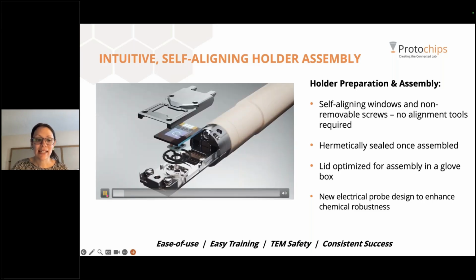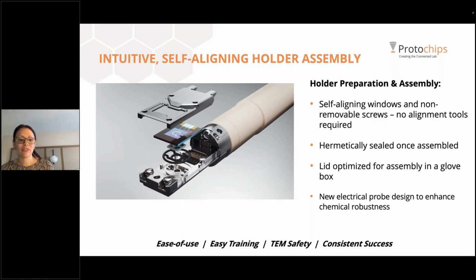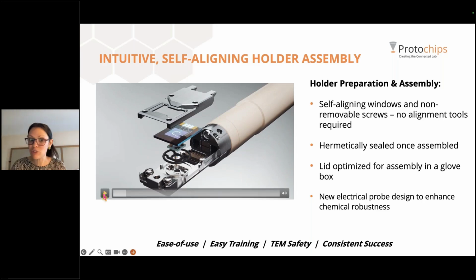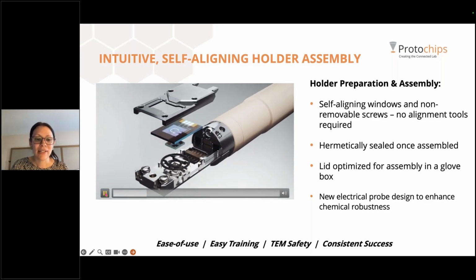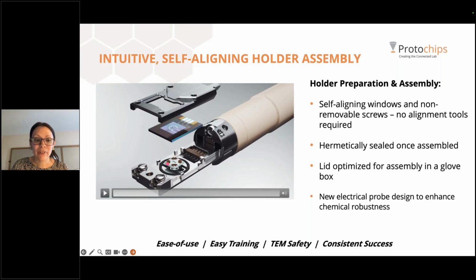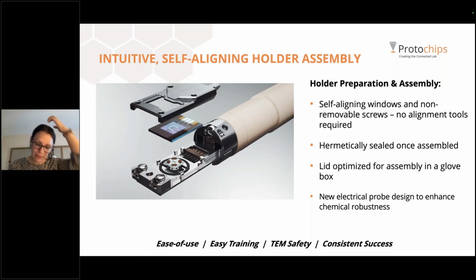So if we look at this again, we've got a single sealing gasket. The one gasket versus multiple O-rings tries to help prevent additional leakage points, minimize the areas where you could get a leak. You've got a small MEMS device that goes in first, which I'll talk a little bit about the specific design. And if you're, again, not familiar with in situ TEM, each of these MEMS devices, these two chips where your sample will go in between, each of them has what we call a window where the electron beam is going to go through from the TEM, and that's where you're going to do your imaging.